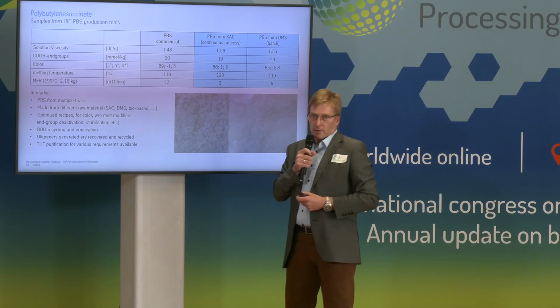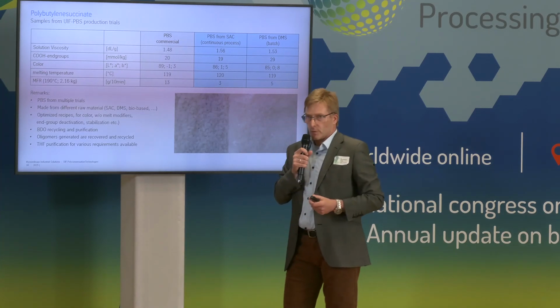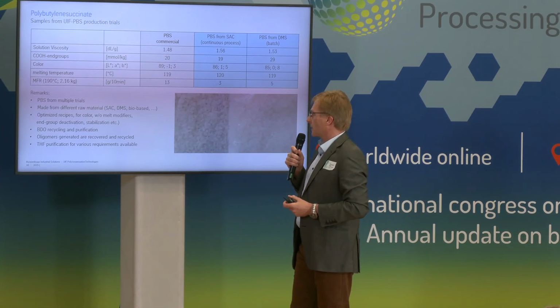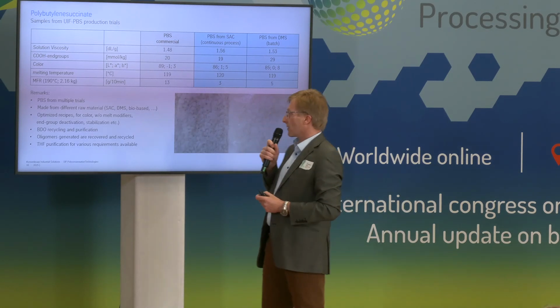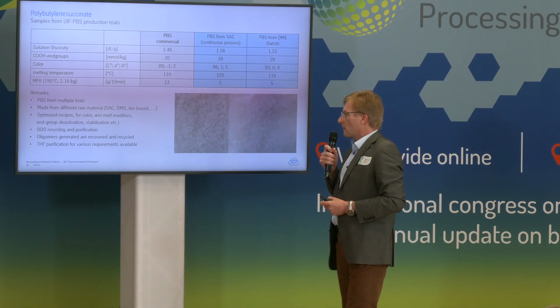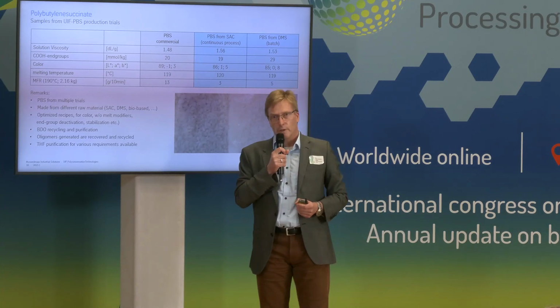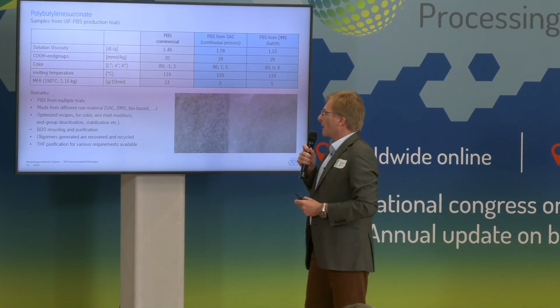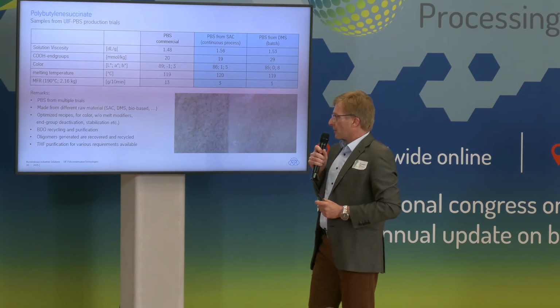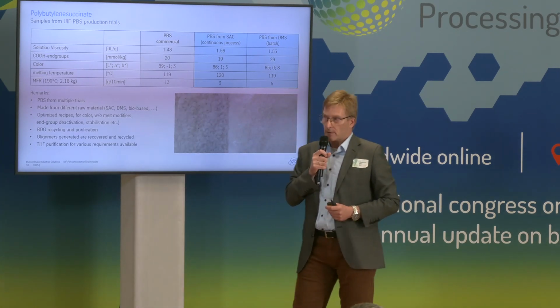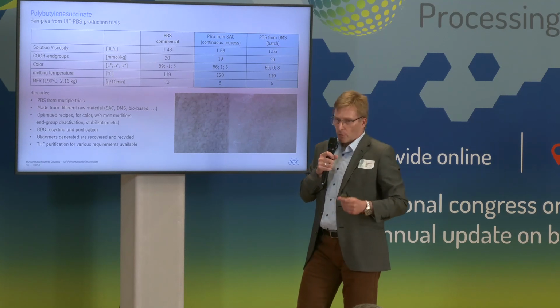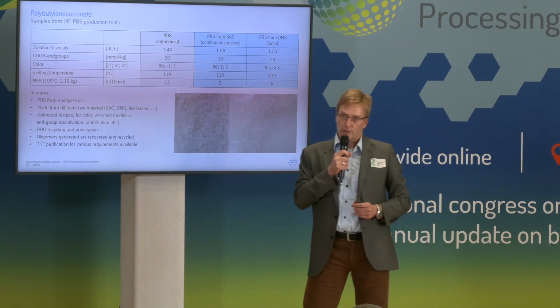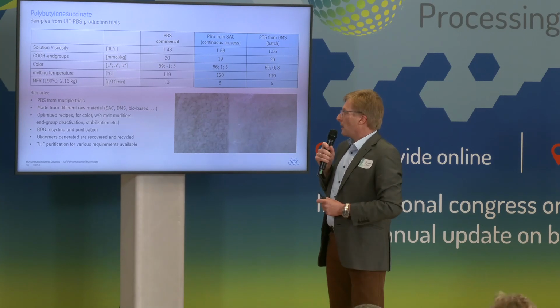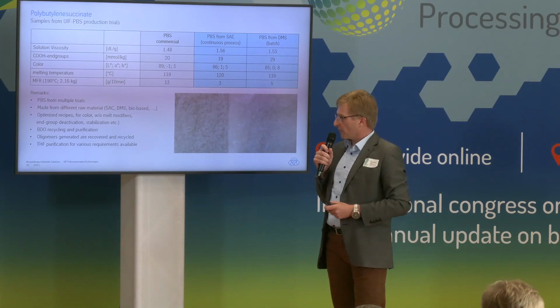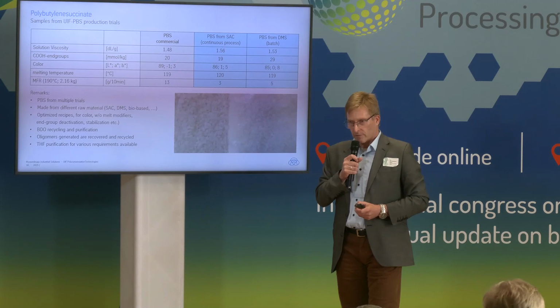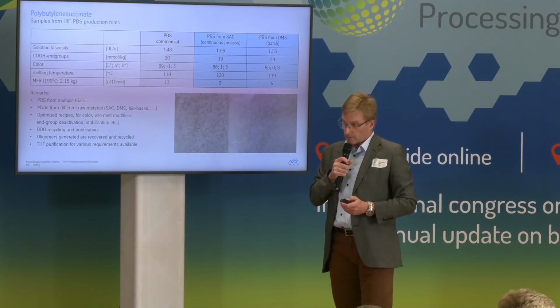We have produced PBS in many trials in the meantime. We have used different raw materials: succinic acid, DMS, bio-based succinic acid. We have optimized the recipe for color. We have played with melt modifiers. We know which extent of melt modifier we want to add. We have looked at end group stabilization and deactivation. We have optimized our BDO recycling system and purification. We know that in PBS production, typically a lot of oligomers are generated. This can also be recycled. And we also have looked into THF purification, and the THF purification can be adjusted to various requirements.